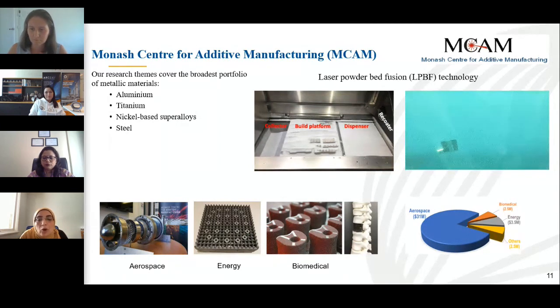We also have to optimize the post-processing heat treatment because, as you know, we are using extremely rapid cooling. It can reach up to 1 million Kelvin per second in LPBF technology. So residual stresses will develop in the part. That's why the post-processing heat treatment is very important to relieve the residual stresses. And in the case of some age-hardened alloys, we are also strengthening the alloy.